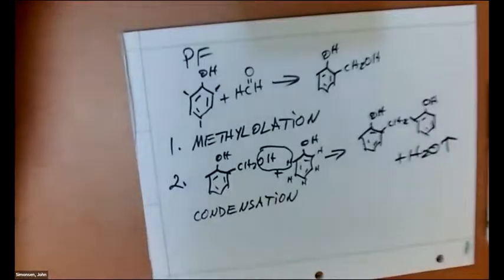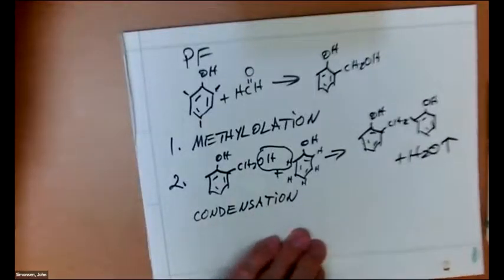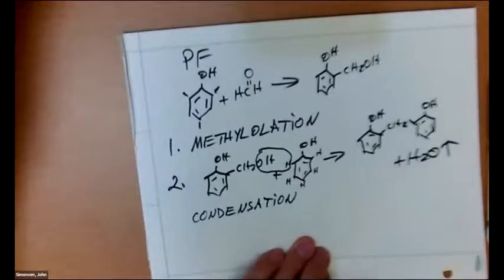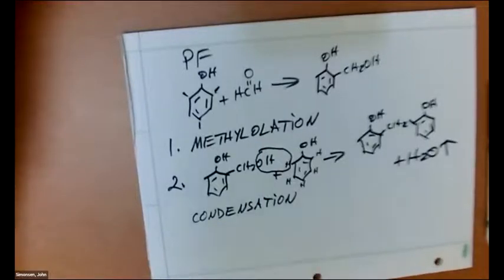And the water is going to go off as steam, because you're above the boiling point when you press these things, 175C when we did the lab, right? Or it's going to soak into the wood and be absorbed by the wood, because you don't want to glue wet wood, right? If you take wood that's above the fiber saturation point, and you put it in a hot press at 175C, it's going to explode. Right? You're going to make steam. And when you open the press, it's going to explode.